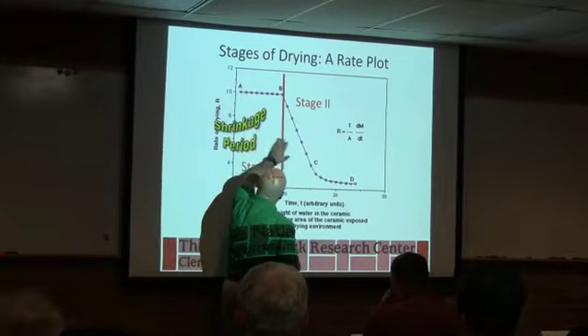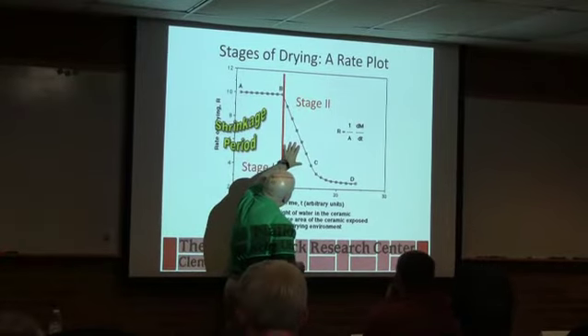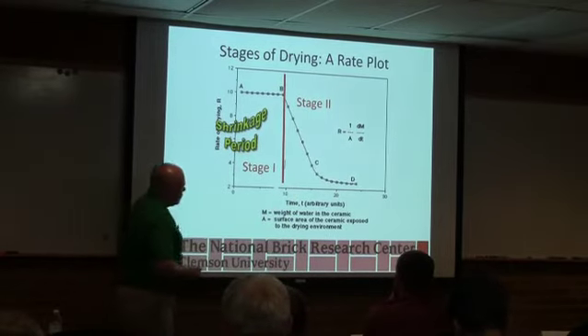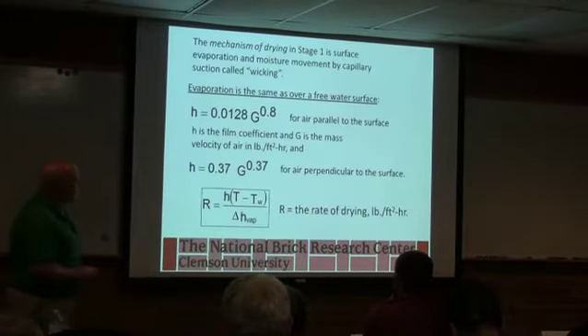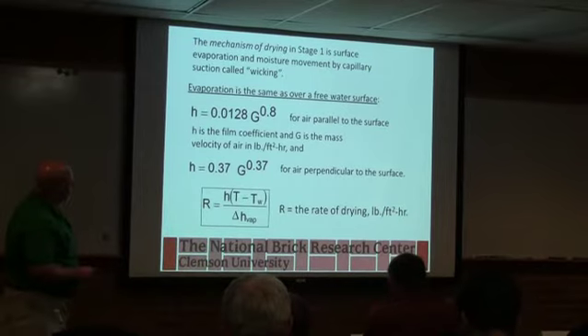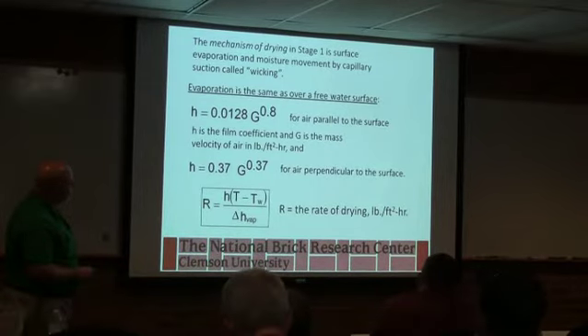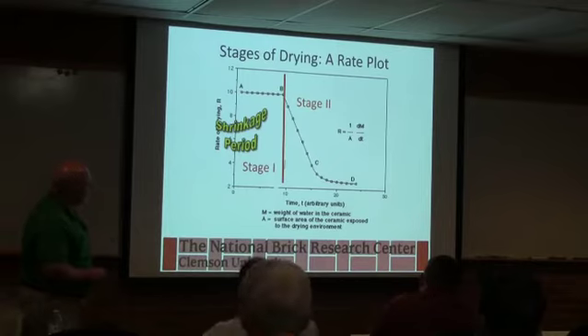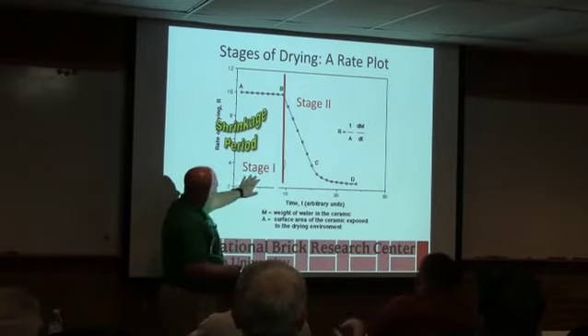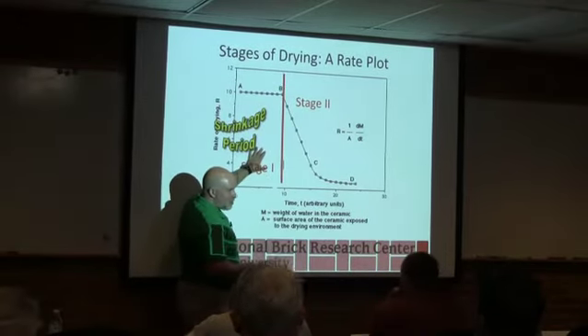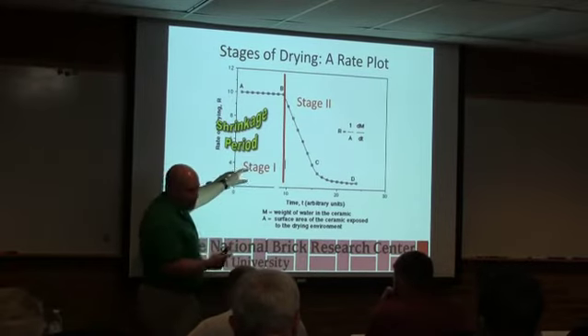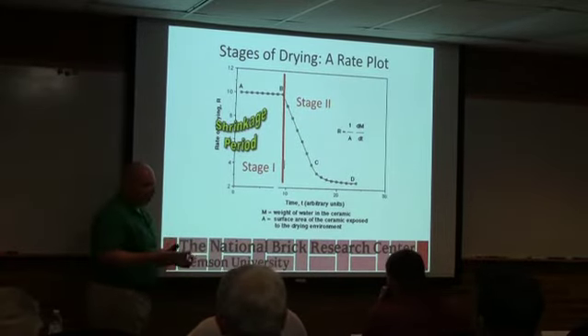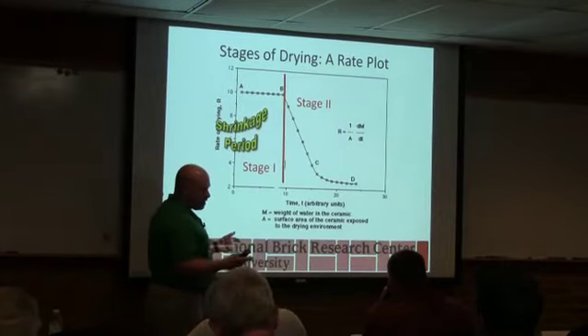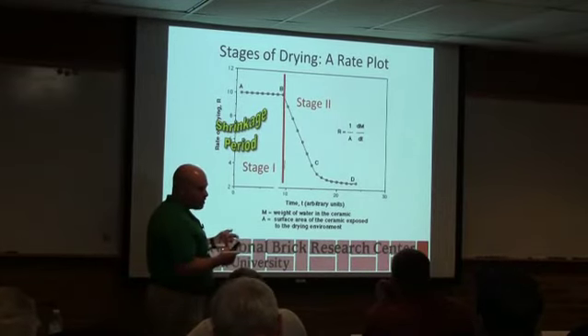So the forming water and shrinkage takes place, and then you're getting into the pore water and the capillary and the hygroscopic water. This has to do with the film coefficients. We won't really spend a lot of time on that, but basically what happens in this first period of drying, evaporation is taking place at the surface. So you've got a continuously wet brick, so it's capable of moving water to the surface and evaporating.